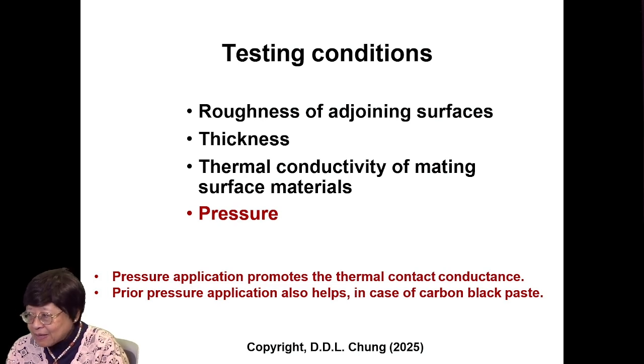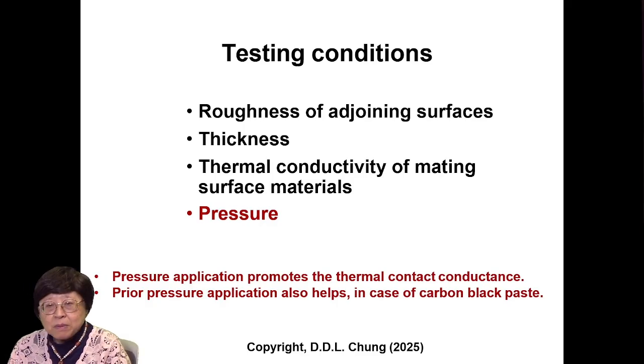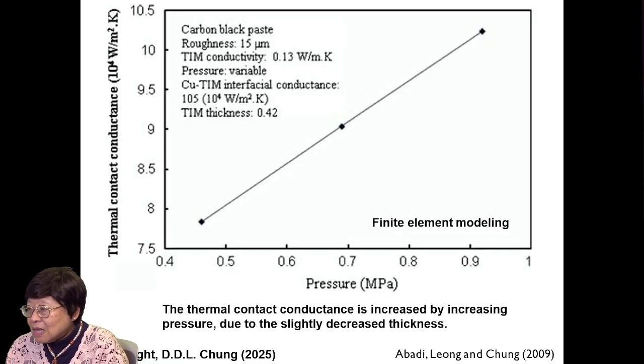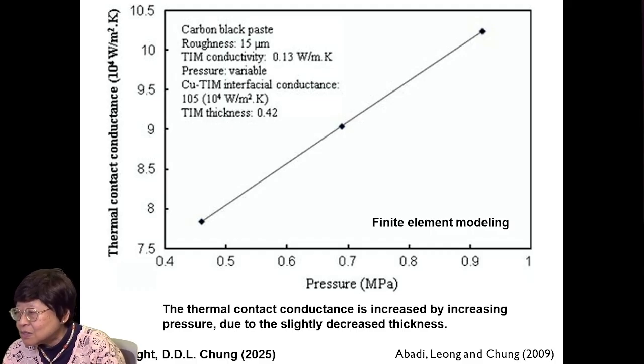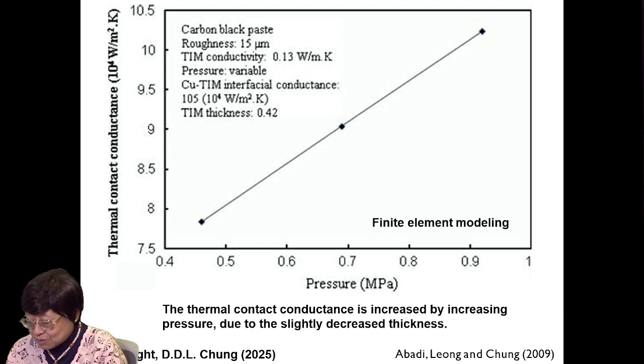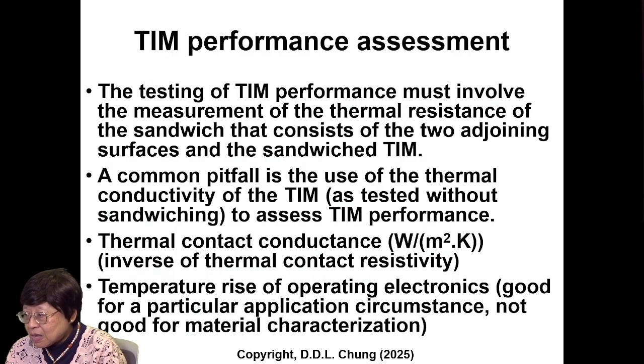Next, pressure, another testing condition. Pressure application promotes the thermal contact conductance, and prior pressure application also helps in case of carbon black paste, at least. And this shows the thermal contact conductance versus pressure with all other conditions fixed. The higher the pressure, the higher is the thermal contact conductance. And this is due to the slightly decreased thickness due to the increased pressure.